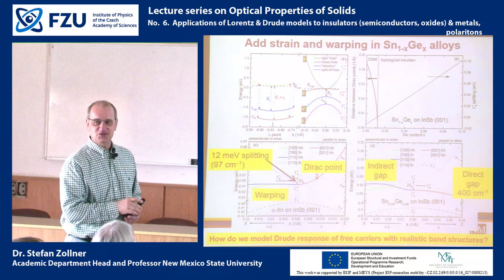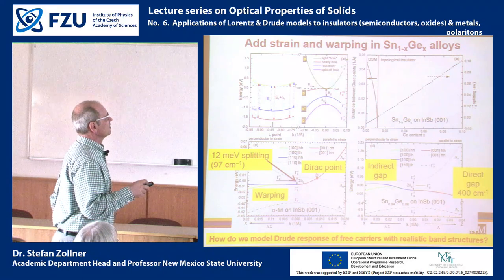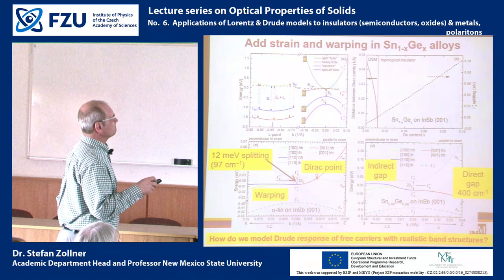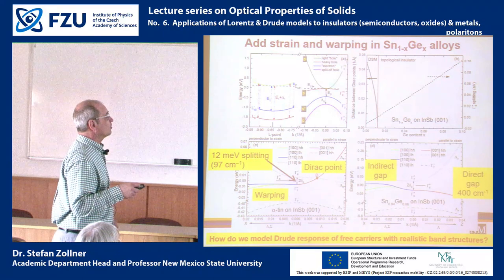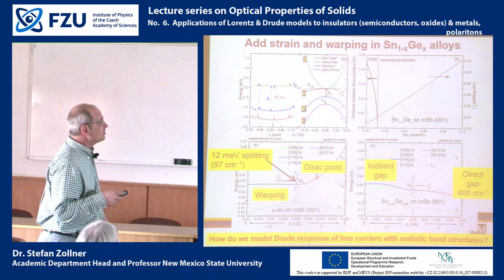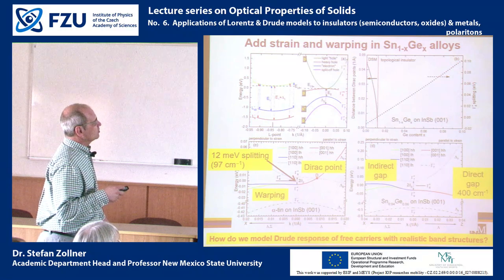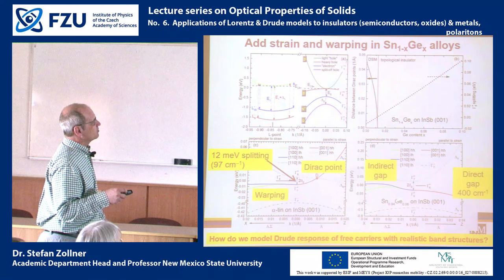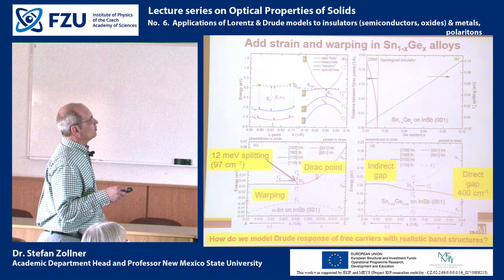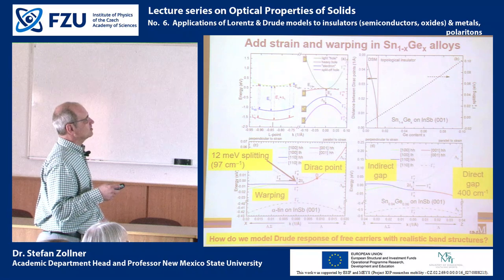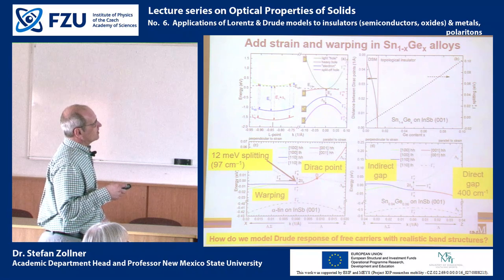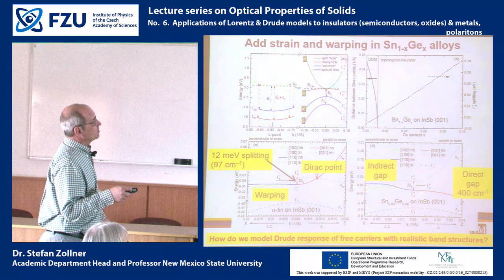And now it really will be interesting to do this experiment and to study the Drude model because we should be able to pick up this Dirac point in infrared spectroscopy. This strain here, alpha tin on indium antimonide, is tensile. We can also add a little bit of germanium to the tin. In this case, 6% germanium is added, and then we can form tin germanium alloys. So by tuning the composition between the germanium and the tin, we can tune the lattice constant. And then we can go from this tensile strain case where we have a Dirac point to this compressively strained case where we have an indirect gap.